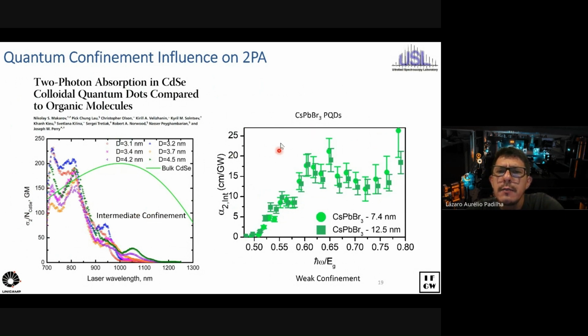Conversely, if you look at the perovskite quantum dots, cesium lead bromide, in the weak confinement regime, these guys are big compared to the exciton Bohr radius. You see that basically the two-photon absorption cross-section divided by the volume, the volume normalized cross-section, let's say it does not depend on the size, and more than that, actually the spectra are pretty similar.